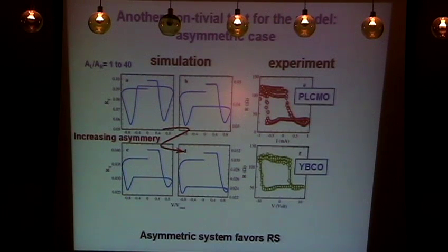As an additional test, we asked: how about if we relieve the condition of symmetry? This we can easily investigate in the model by just changing the ratio of the coefficients AL and AR that describe the Schottky resistance in the two interfaces. So instead of having a ratio equal to 1, we decrease one of the two and get a set of data from the symmetric system to a very asymmetric system where we decrease the resistance of one of the two interfaces. And what we see is that this goes from this symmetric-looking state to something that looks more reminiscent of the simple high-low switching.